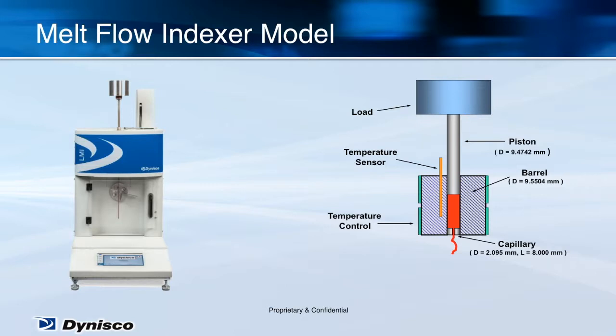MFI is a measure of the ease of flow of the melt of a thermoplastic polymer. It is defined as the mass of polymer in grams extruded in 10 minutes using a specified test method, such as ASTM D1238 or ISO 1133. In the method, polymer is heated to a defined temperature, then it is driven through a capillary with a defined diameter and length by pressure created loading a piston with a defined weight.